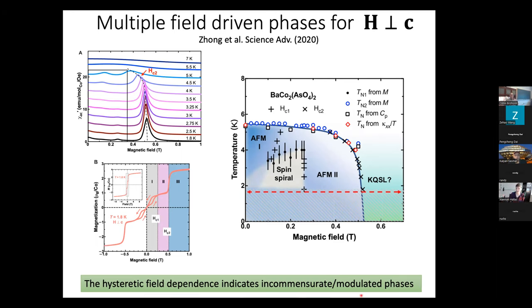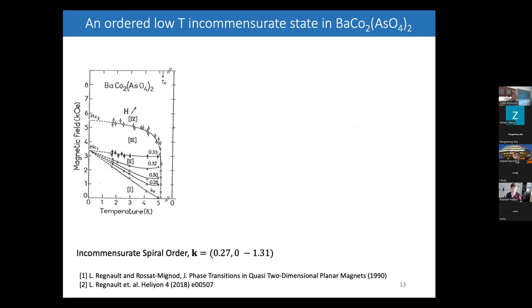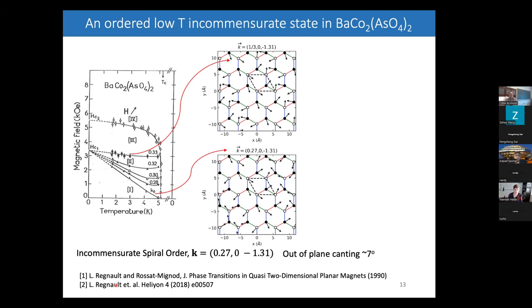Any other questions? Yeah. So Collin, has the spin spiral structure been completely solved in the intermediate phase? I think it pretty much has. And I refer you to this very nice paper published in a rather unusual place, Heliyon, 2018. It's a real treatise, and they go through in great detail the use of the cryopad method, a polarized beam technique to determine the spin structure. This is really the gold standard for how to determine these spin structures. I think they've done a very thorough job on that. I think the state is actually known from this work. And here are pictures of these spin structures. They make distinctions that are not possible using conventional unpolarized methods. It's really a very beautiful work.